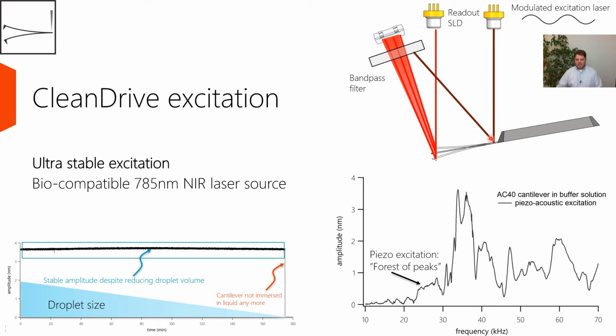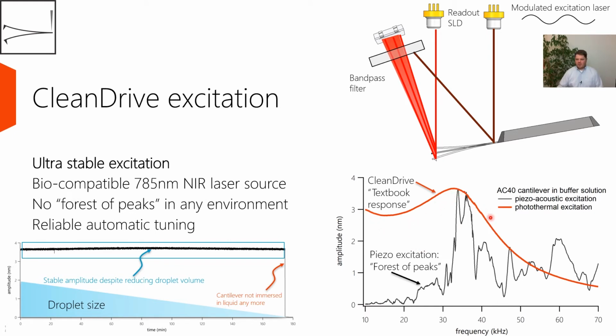What you see if you do piezo excitation is that you typically get such a resonance response in liquid. If you do that now with clean drive, you get a very textbook-like response. You have one single resonance peak that you see. And this allows you to reliably and unambiguously tune where you want to drive or excite your cantilever, at which frequency, at which amplitude. This forest of peaks will change every now and then during operation in liquid when using the piezoacoustic excitation. And it will also change when you change the distance to the surface, things like that. So it's rather unstable.